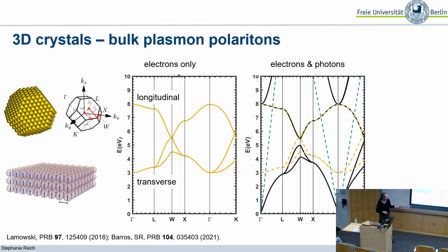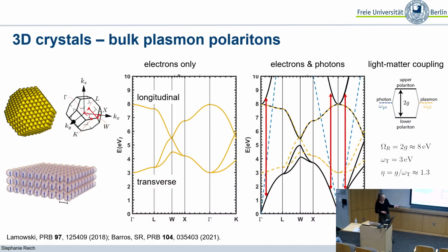But then when you look at the point where the transverse plasmon and the photon cross, you can see that there is a huge anti-crossing that extends over several eVs. So this is the coupled state after I put in the photons, the coupled lower polariton and the coupled upper polariton. So this corresponds to the sketch that I showed you a couple of slides ago, only that the splitting is way, way larger than it was in the first examples. And we extracted here the Rabi splitting and the light-matter interaction strength. The Rabi splitting is 8 eV, so the light-matter interaction strength is 4 eV.